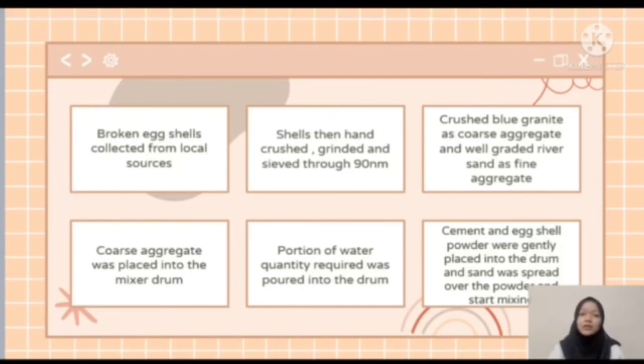Fourthly, coarse aggregate was placed into the mixer drum, and a portion of the required water quantity was poured into the drum. Lastly, cement and eggshell powder were placed into the drum and sand was spread over the powder and mixing started. The percentage of eggshell powder that replaces cement in this concrete is about 15%. The remaining mix design water quantity was added into the mixer drum during the mixing process to ensure full mixing of the ingredients. After that, the specimens were prepared and left for 24 hours before being demolded and put in normal water to cure till the test age.